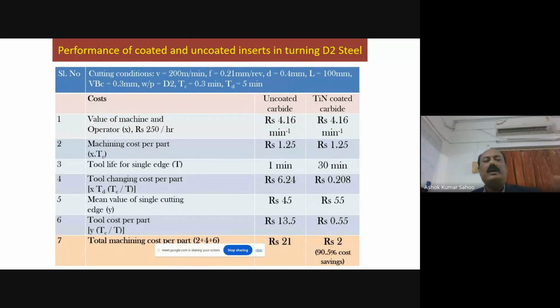uncoated carbide insert. So in order to compare the performance of the two inserts, an economic analysis has also been calculated. The tool life of the uncoated carbide cutting insert is 1 minute to failure, while the titanium nitride coated insert goes up to 30 minutes to reach the flank wear limit of 0.3 mm. So the tool life is 30 minutes for the titanium nitride coated carbide insert. For the comparative economic analysis, as per Gilbert's approach, there are different cost components: the machining cost, the tool changing cost, and the tooling cost. The addition of the machining cost, tool changing cost, and tooling cost is called the total machining cost per part.